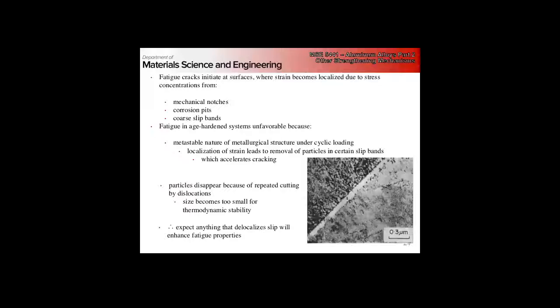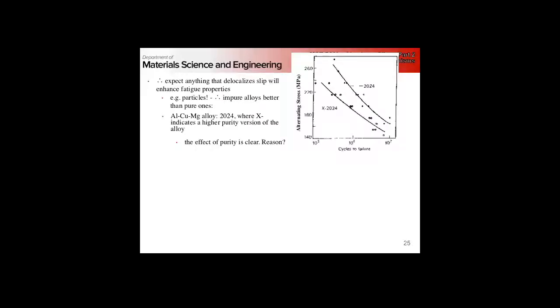So our strategy is, strain localization is bad. So the strategy to improve fatigue resistance is we want to do anything that we can to try and delocalize slip. Okay? So some slightly larger particles rather than just the strengthening ones.